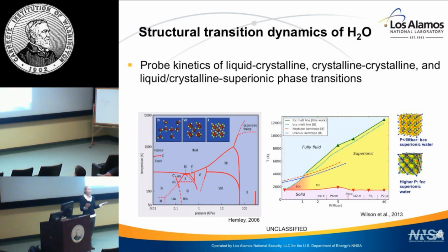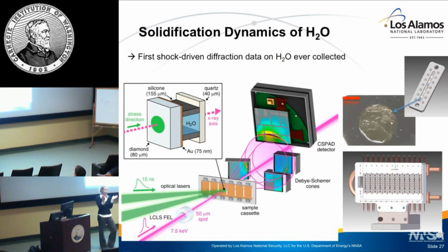Okay, so we have our package of liquid water that we start with. My little cell that I fabricate is here, so it's sandwiched between diamond and quartz, both of which are single crystal. So I should not see any polycrystalline evidence from them in the X-ray diffraction pattern. Our water will give a diffuse signal. Okay, same idea here. We send in our optical laser to drive the shock. We probe with the XFEL, with the X-ray free electron laser, and at certain time delays, I probe, collect that diffraction. Okay. These targets were extremely challenging to make.